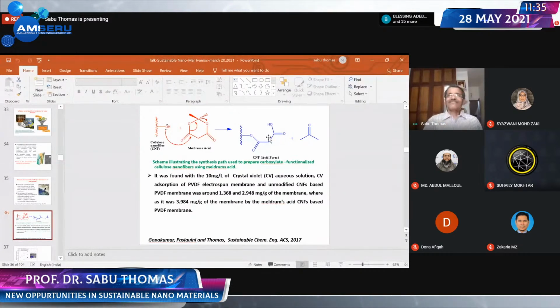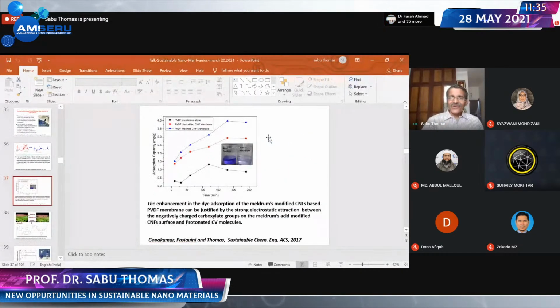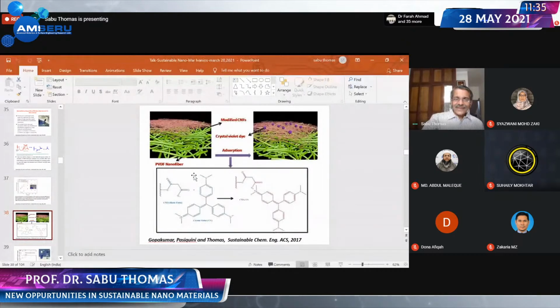Once you do that, you know what is the beauty? The modified cellulose, with negative charge, COO minus, can trap the crystal violet dye by electrostatic interaction. Look at this electrostatic interaction between the modified cellulose and the dye. And you see all the dye particles could be retained at the top of the filter by electrostatic interaction.